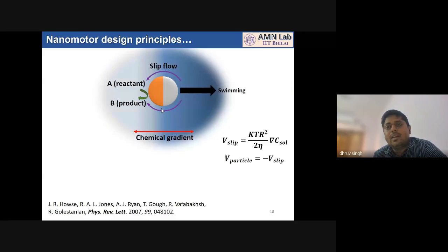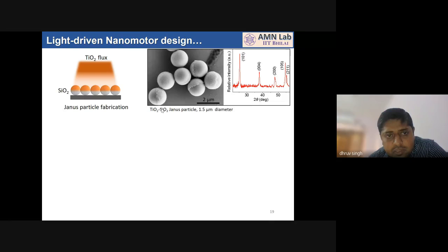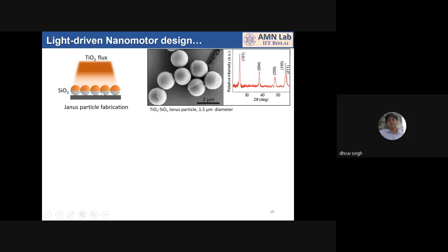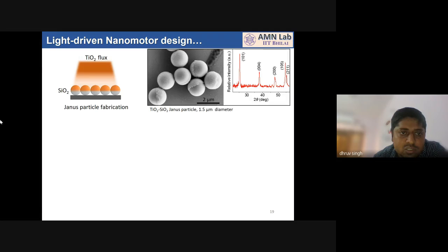To fabricate this type of motor, I started with a very basic principle. I formed a monolayer of silica particles, which are commercially available in different sizes. This is how we can form the monolayer. It looks like this if you see it from the side as a cross-section view. Then you deposit some TiO2, for example. TiO2 is a photoactive material. If you deposit it from the top, it will automatically cover half of the particle, because TiO2 coming from the top cannot reach the other side. So it will coat it half, and if it is half coated, you can call it a Janus particle.